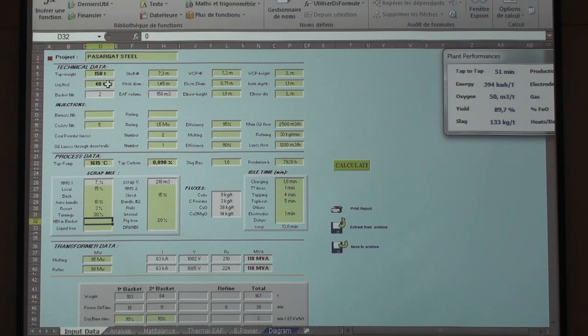And one more thing about why they encourage the hot heel: one is the slag. They do not want the slag to carry over to the ladle. 5 kilograms per ton of slag carry-over is normal. But in the case of the BOF, 2 or 3 kilograms per ton is normal, because they have a stopper. Operators can do it in the case of POSCO. They are very skilled, and they cut the ladle, cut the slag, and they can make it.